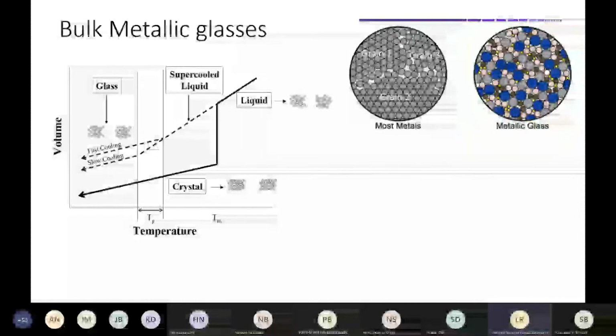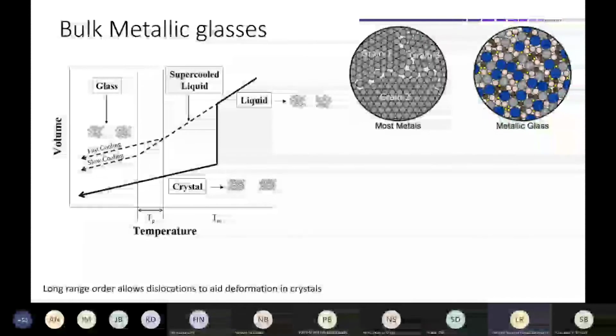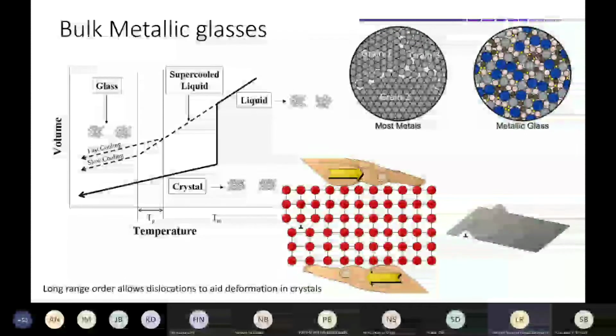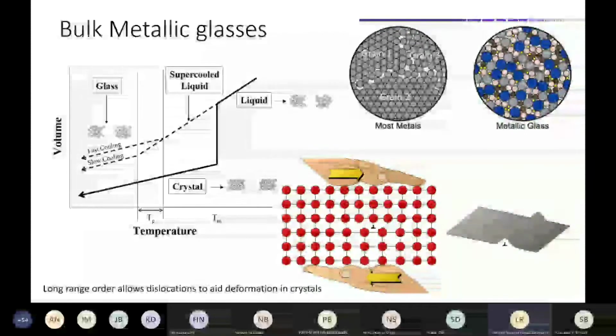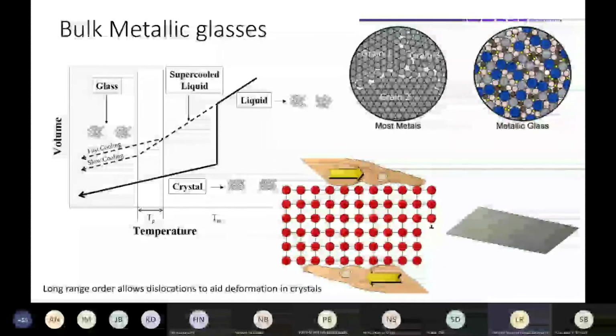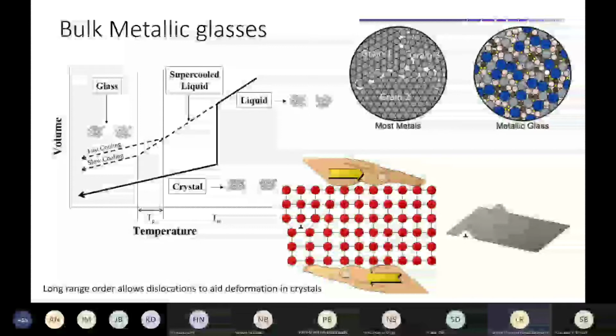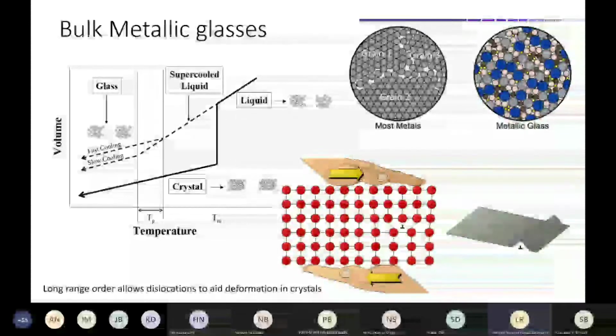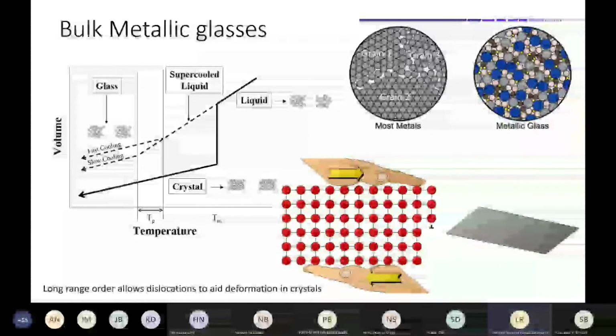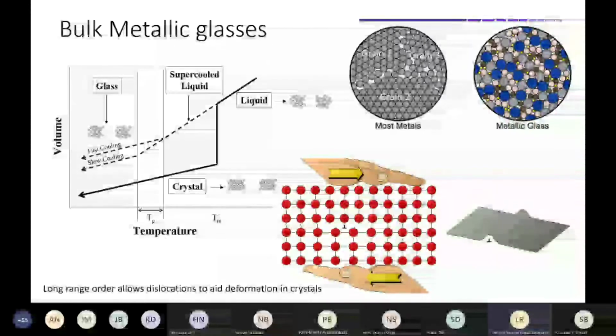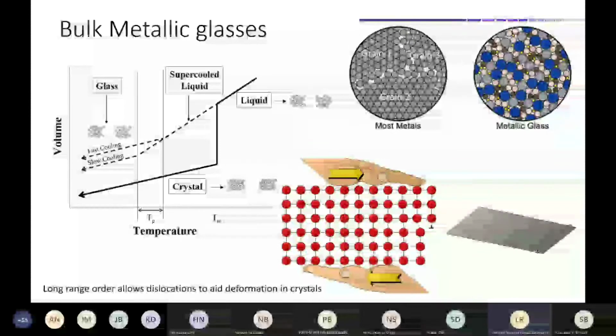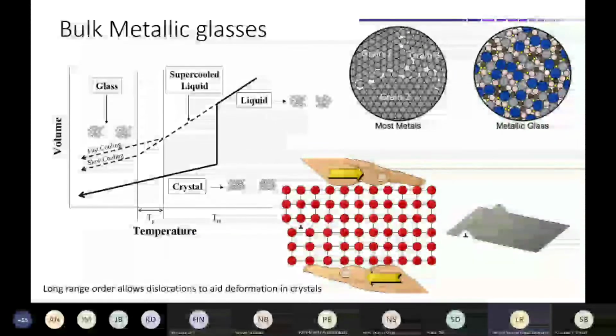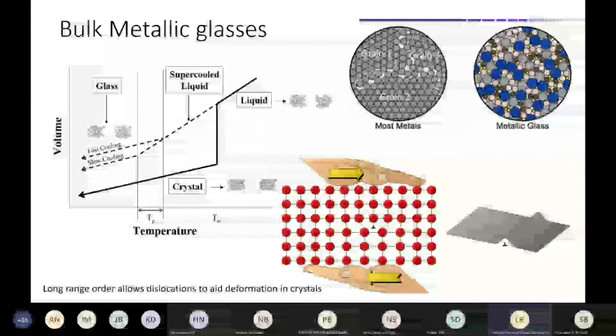The feature that you need to remember is that in grains, because of this fixed orientation, you are allowing dislocations to be inside the crystal. You are able to define something called a dislocation. And what are dislocations? This is something you would have seen in your mechanical metallurgy. I'm not sure if you have a course on mechanical metallurgy, but nevertheless, what happens is there is a plane of atoms which is going to move relative to the other. If you can see this GIF that I have posted here, when you shear an object, you essentially create a small dislocation which looks like an inverted T, and that moves across the crystal and cuts through it. So you are able to accommodate plastic strain by this dislocation.